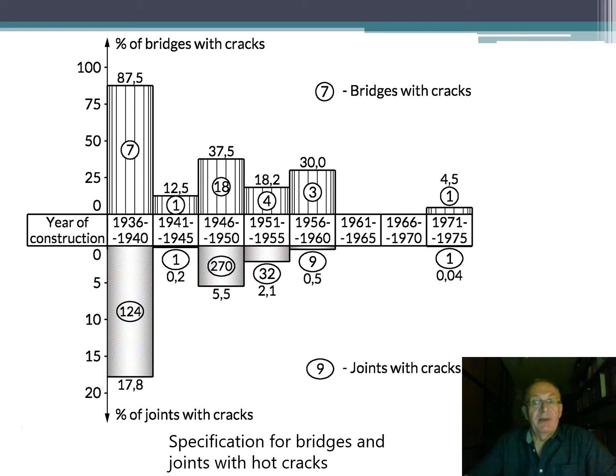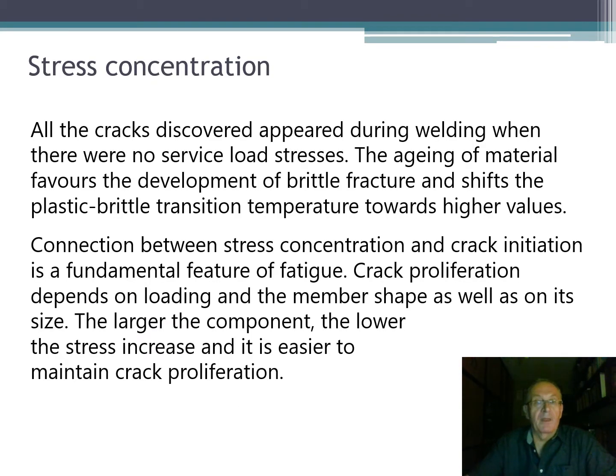The situation for the period after the Second World War is that many bridges were constructed with poor quality of welds. In 18 bridges, technological cracks were discovered, so it means that in 37% of the bridges tested, cracks appear. The total number of cracked joints for that period is 270. All the cracks discovered appeared during welding, when there were no service load stresses.